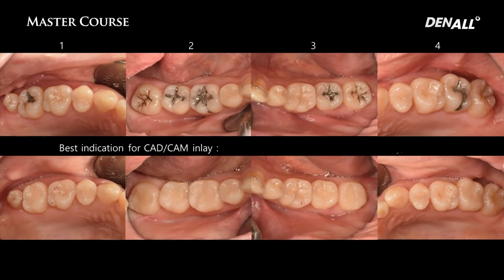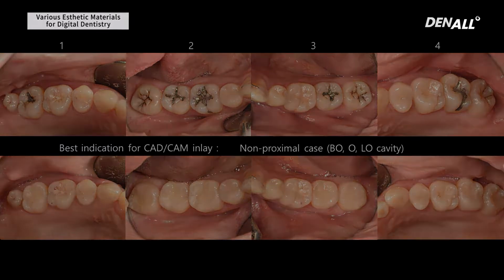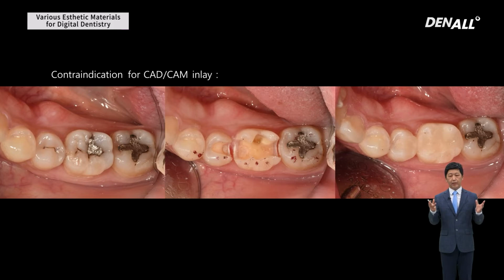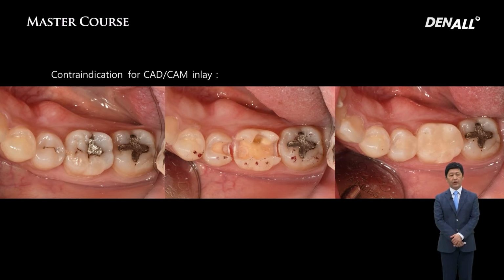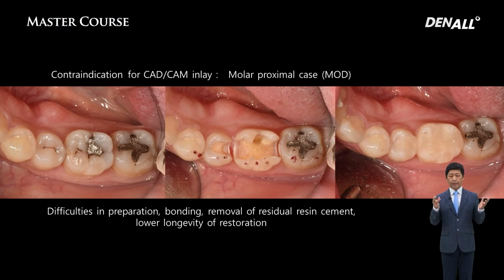Best indication for inlay using hybrid resin ceramic. The best indications would be non-proximal case like BO cavity or O cavity or LO cavity. If contact points are in many different areas, like in this very complicated cavity, I would recommend the crown rather than hybrid resin ceramic because it is very difficult to prepare a tooth and it is very difficult to bond the prepared tooth and to remove residual resin cement. And also, the material's longevity is not very long, so in the follow-up, the restoration would be found to be fractured in many cases, so a crown is recommended rather than hybrid resin ceramic.